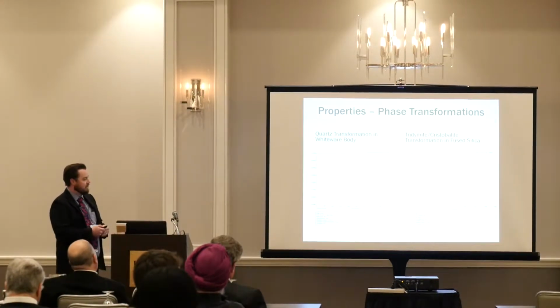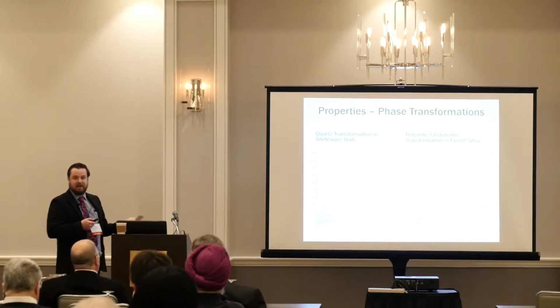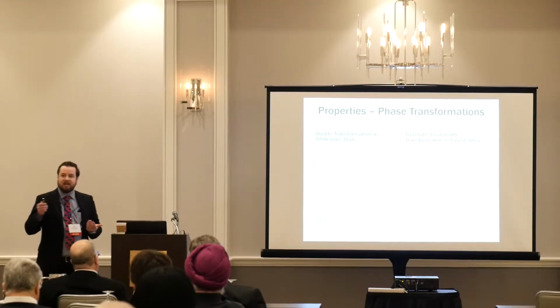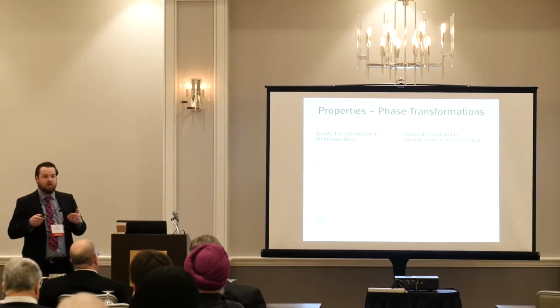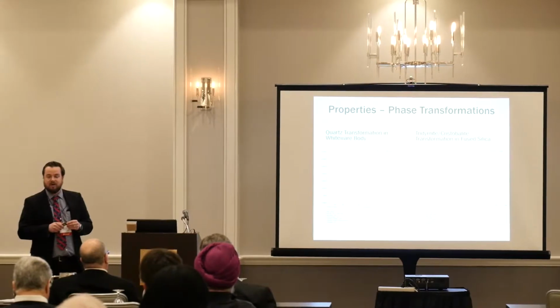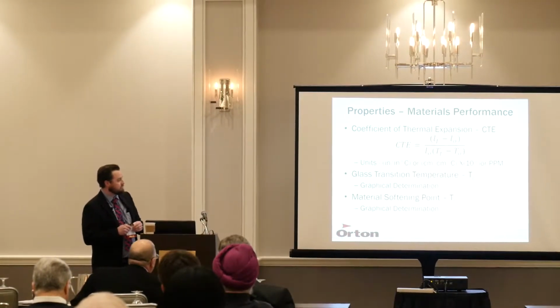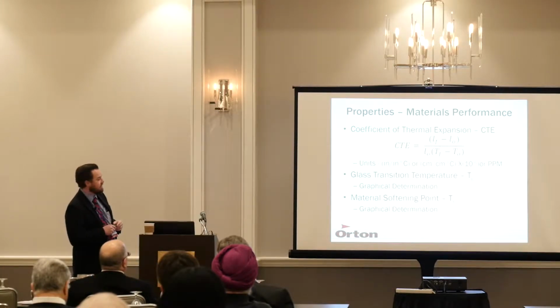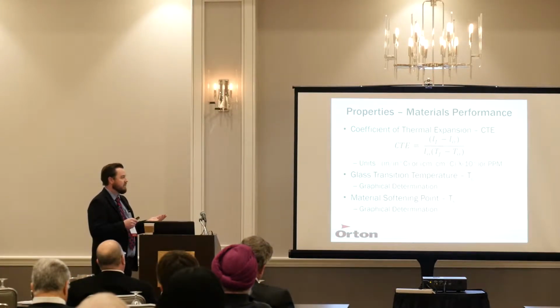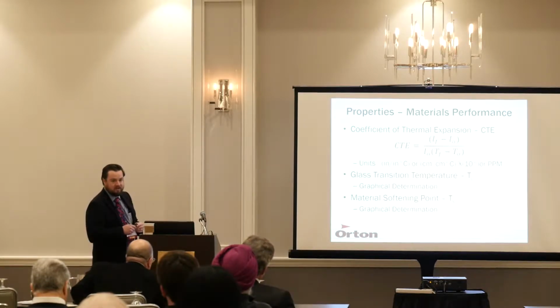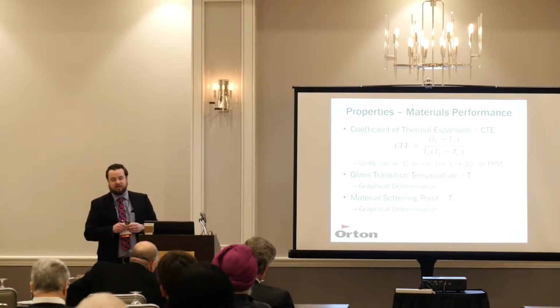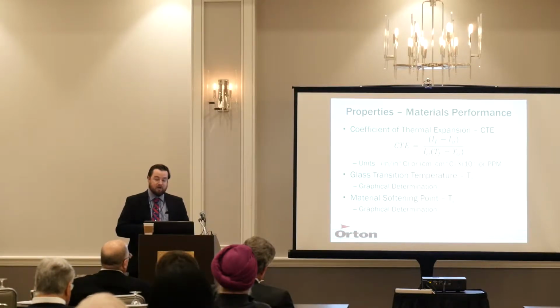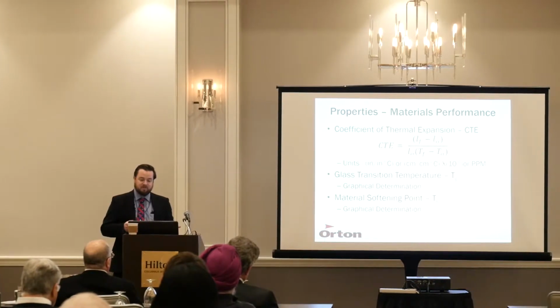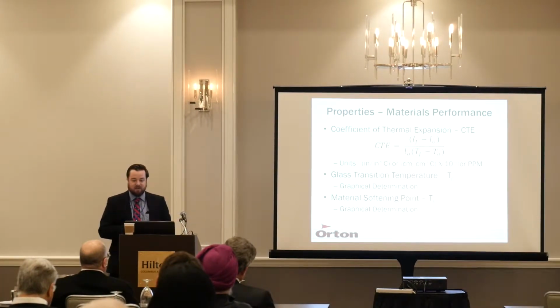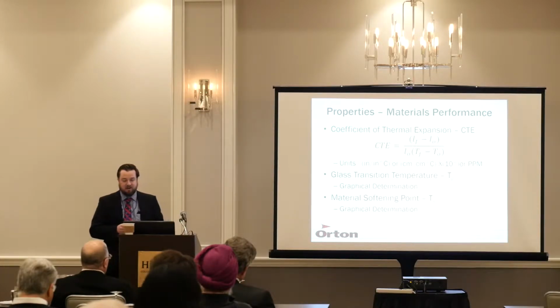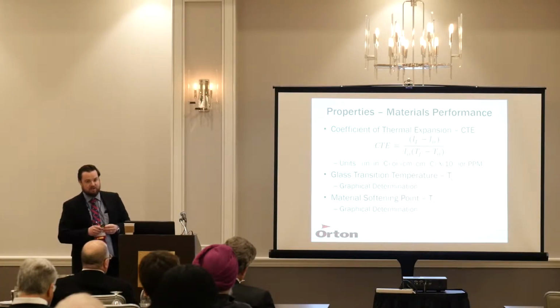So once again, and I think I haven't alluded to this yet, there's heating and cooling. So you can look at how the material is going to perform on the heat up, and hopefully no changes, or all reversible changes. The cool down will have a very similar, if not identical, linear slope. What are the calculations? The beef of this is the coefficient of thermal expansion. How is it measured? It's really straightforward. It's a linear change over a temperature change based upon the initial linear length. The units, as I mentioned earlier, are inches per degree C, or centimeters per degree C, or parts per million, given the fact that you're typically at 10 to the negative 6. So the part per million is not a concentration there, it's used as a ratio.